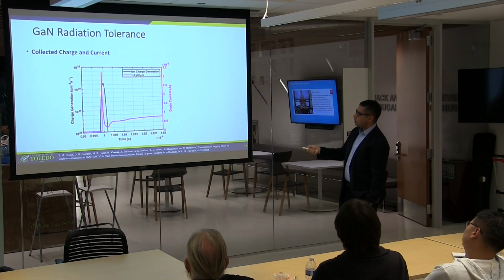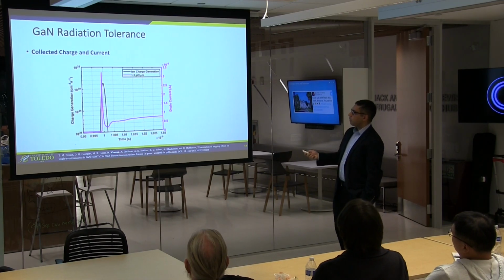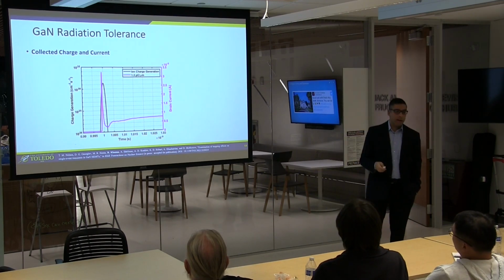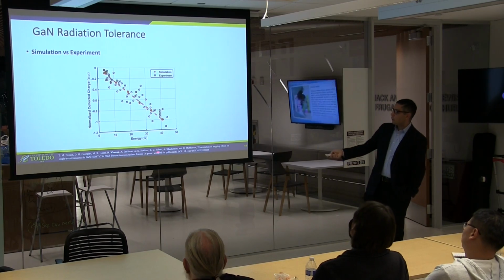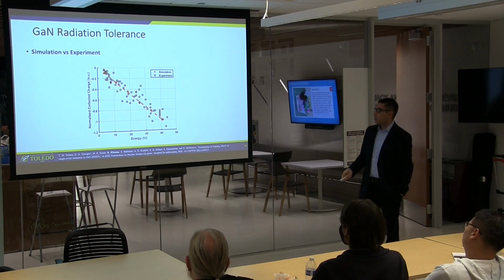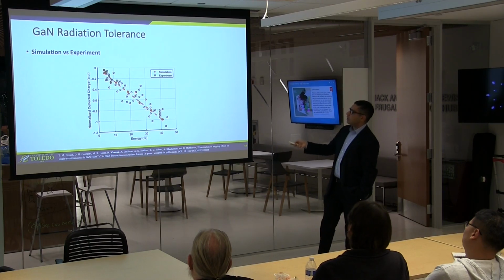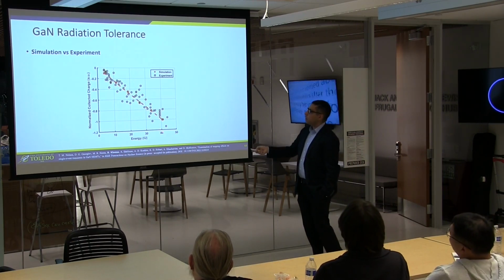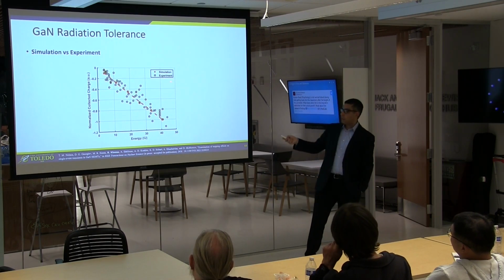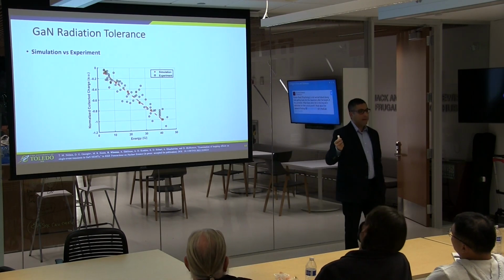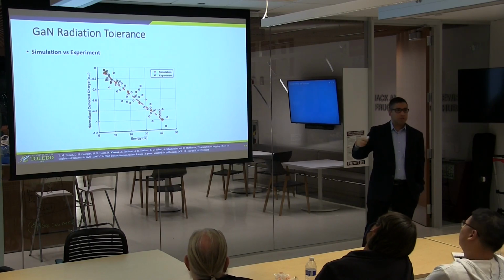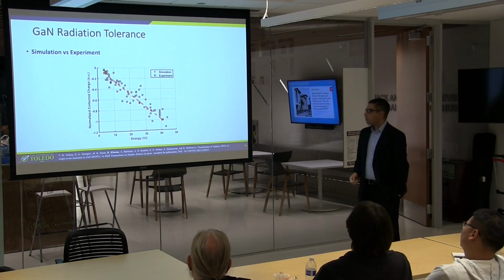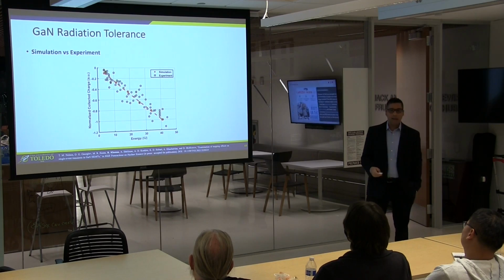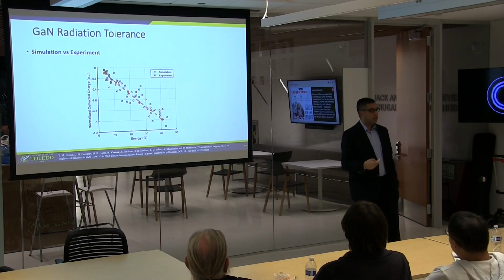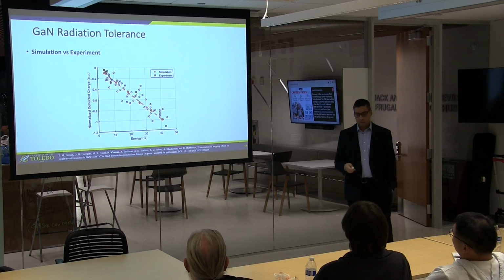basically took a look at the charge collection and the current as well. And this is all from both TCAD as well as an experiment, which I'll show you on the next slide. Again, we just published this in Transactions on Nuclear Science. And you can see that the simulation can be used on average to capture what the experiment is doing. Again, this experiment is two-photon absorption, not heavy ions, but there's been previous work that shows that those two give similar results. So another cool thing you can do with TCAD, gallium nitride particularly has some great radiation tolerance, really good for pushing the limits in space.